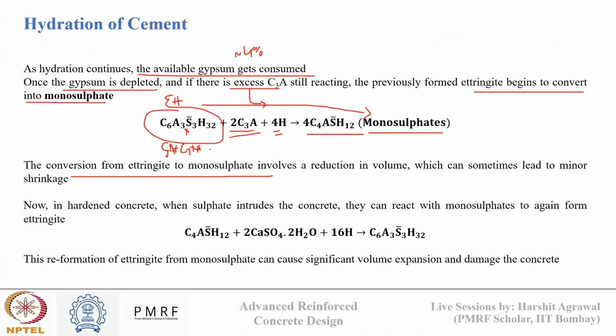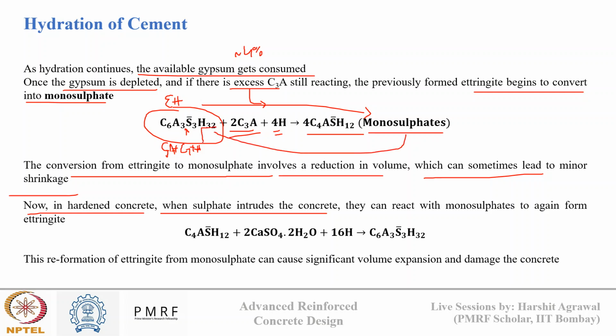Okay. So this conversion involves a reduction in volume, which can lead to some minor shrinkage problems initially during hydration. Now, in hardened state, when sulfate intrudes the concrete, what happens? This monosulfate will again try to convert back to ettringite, and this is known as reformation of ettringite, which can cause significant volume expansion and damage in concrete.